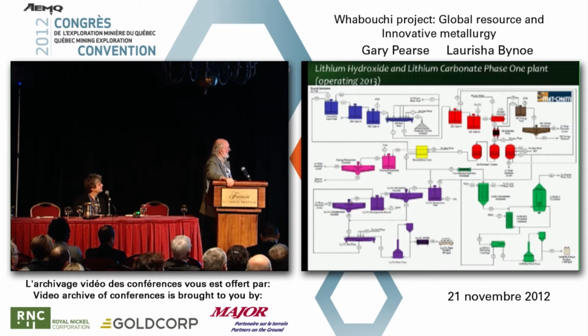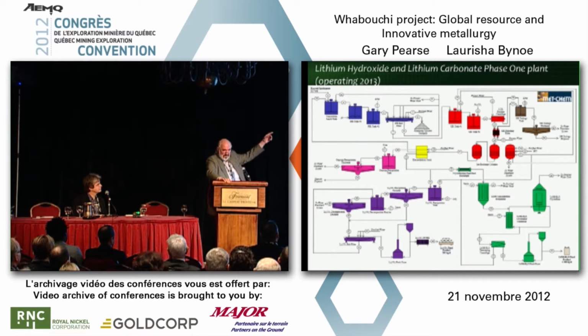We'll be producing 400 tons a year of lithium hydroxide and about 65 tons of lithium carbonate. The beauty of the combination is when you make the lithium hydroxide monohydrate, the efficiency of that crystallization is only 75% recovery, and you end up with a purged solution rich in sodium hydroxide that also follows the lithium all the way through. And this is ordinarily a waste product. We use it to feed back for altering the pH in the solution and then recapture the lithium units as they go through. And we also can send the purge solution directly to the lithium carbonate precipitation circuit and produce lithium carbonate from this otherwise waste solution.